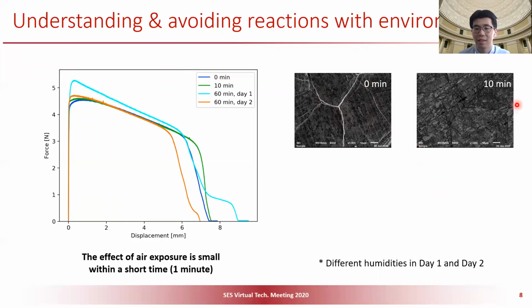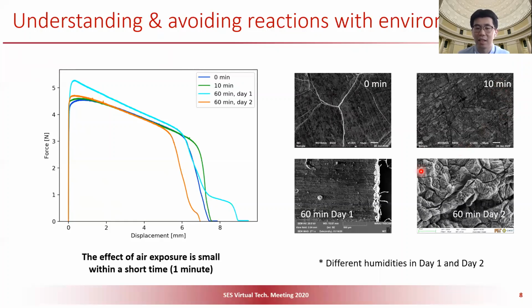So 10 minutes, oxidation and humidity play a very important role. On different days, after 60 minutes, you will see a very, very rough surface quality for the sample. So this is the power of exposure to air. In our test, we avoid this by putting it in an argon atmosphere, and we also developed some small devices to finish the test. And above all, we do all the tests within a very short test duration.